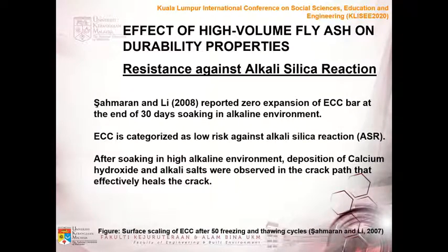Then resistance against alkali silica reaction. Sahmaran and Li in 2008 reported zero expansion of ECC bar at the end of 30 days soaking in an alkaline environment. ECC is categorized as low risk against alkali silica reaction. After soaking in a high alkaline environment, they also found the deposition of calcium hydroxide and alkali salts in the crack path that effectively heals the crack. So we can also say that it is good against alkali silica reaction when we use high volume fly ash.